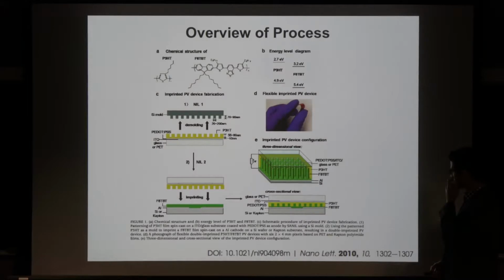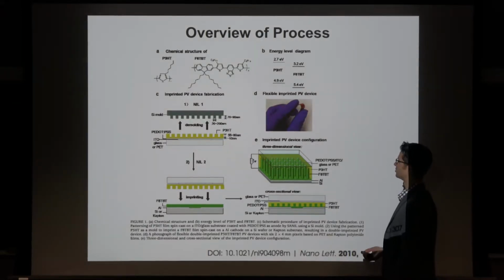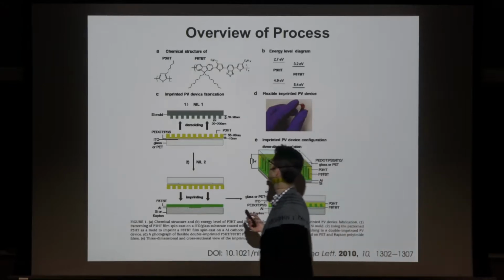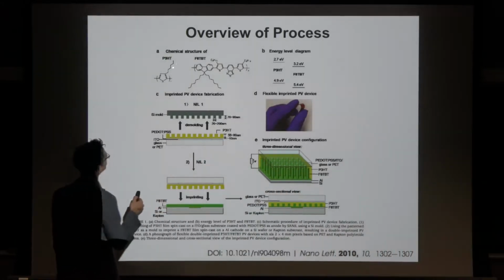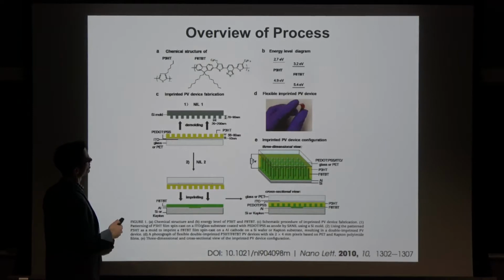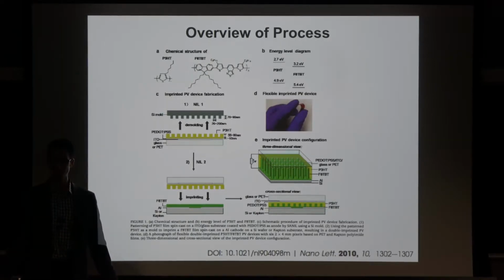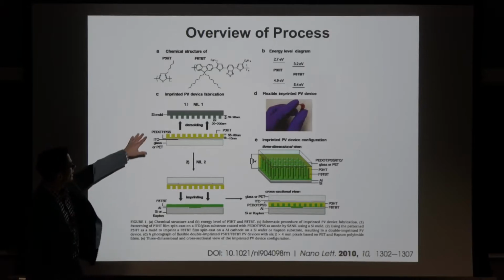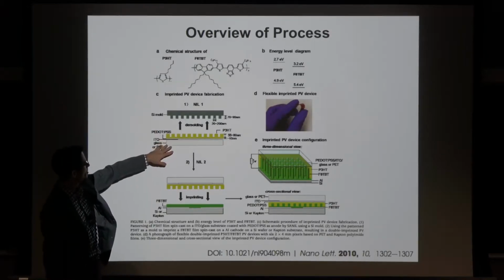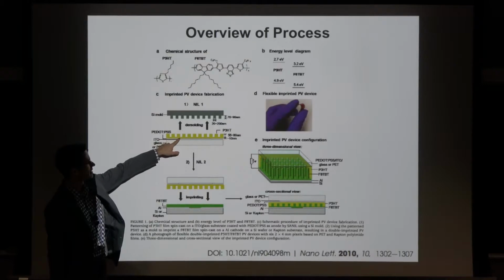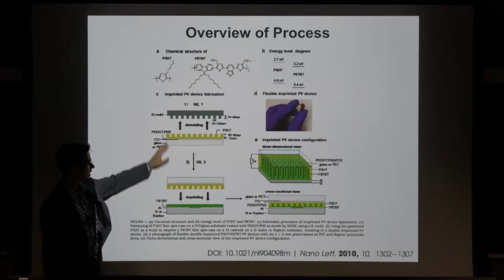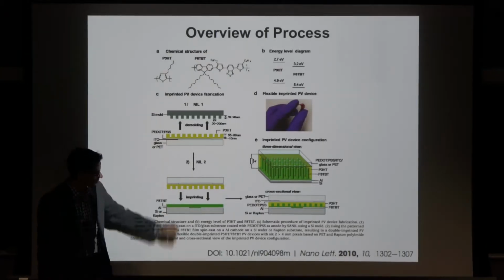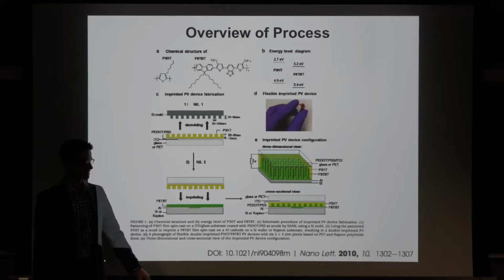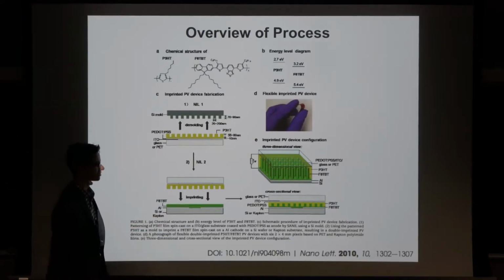And this work was done by Richard Friend's group and others at the University of Cambridge, where they took these two materials. This is the electron donor and the electron acceptor. And what you do is you take a silicon mold that you've made by electron beam lithography, and you press it into one of the polymers to make these nanostructures. And then you take this and then you press it into the other polymer to make this interdigitated heterostructure.